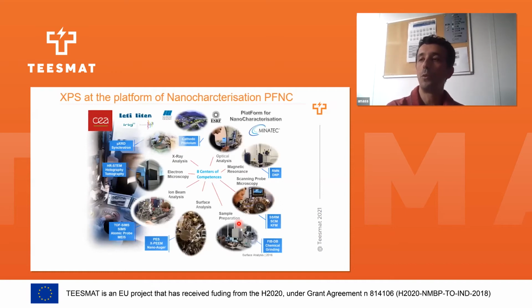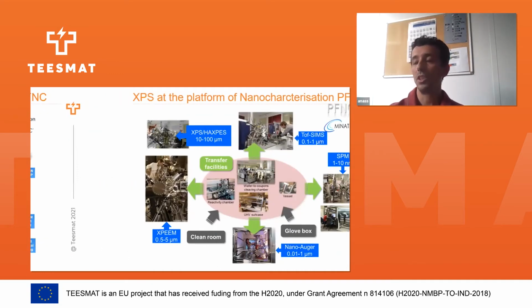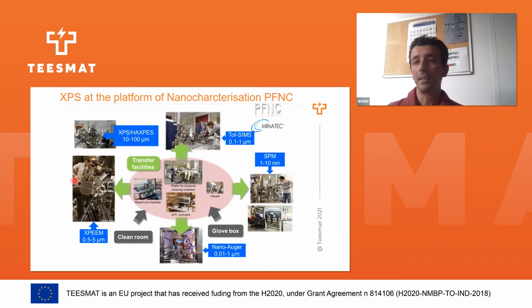And just like before, to go further, this is the XPS at the characterization platform at CEA, which is a platform that holds different techniques and different centers of competencies. My center of competencies is surface analysis, which is organized as follows. We have different surface techniques, including ToF-SIMS, XPS and HAXPES, XPEEM, X-ray photoemission microscope, Auger spectroscopy, and AFM or scanning probe microscopy. What is interesting is that all those techniques are connected to a glove box or clean room, and we can transfer the sample in inert atmosphere without any air contamination. That is important for battery materials.